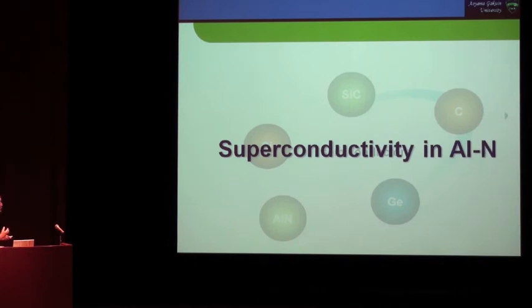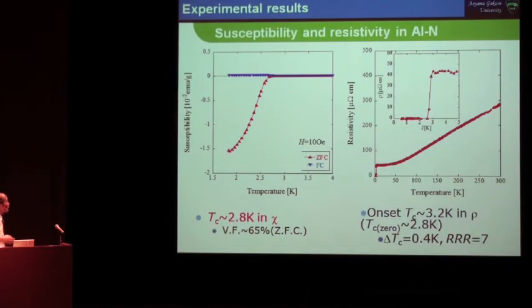Next step is superconductivity in aluminum nitride. You know that aluminum nitride is a famous transparent semiconductor. However, by changing the aluminum ratio of the aluminum nitrogen, we can get superconductivity. TC is 2.8 Kelvin in Chi, and onset temperature of 3.2 Kelvin in rho.